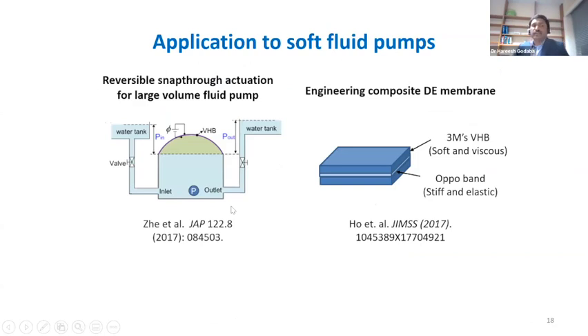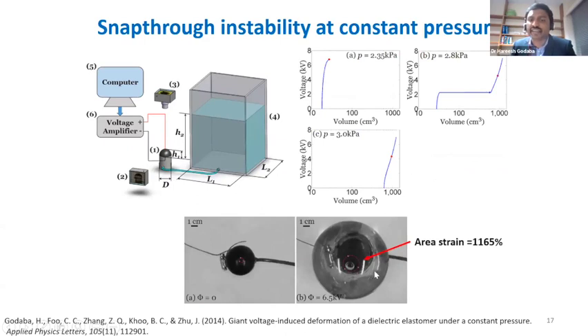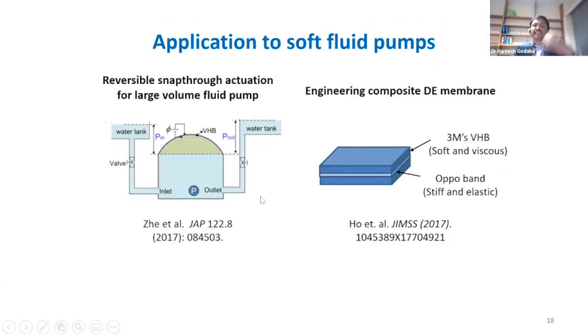So then we collaborated with colleagues in biomedical engineering, and we worked on developing fluid pumps that have potential application for cardiac assist device. In one of the works, we utilized this reversible snap through actuation to achieve a large volume fluid pump. The snap through increases the volume change, and also it increases the flow rate of the fluid. The initial membrane that we used, which you can see here, is a dielectric, 3M's VHB tape.